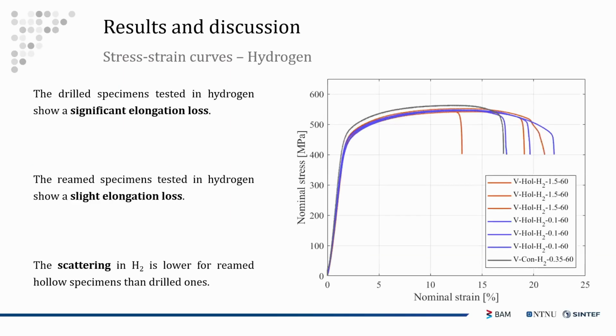Considering here the stress strain curves obtained in a hydrogen environment, we can see that the drilled specimen manifests a significant elongation loss, while the elongation loss for the reamed specimen is lower. And also there is a lower scattering for the reamed specimens, depicted with the blue lines, compared to the drilled specimen in red lines. The black line is for the conventional test conducted with a solid specimen, which is basically the average of the other tests.